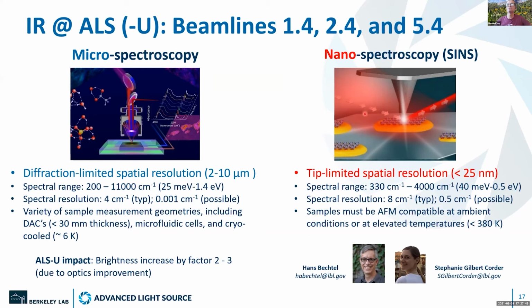This is a very ingenious trick to bypass the diffraction limit, in that the infrared beam is interfaced with an AFM tip. The scattering of the infrared beam off the AFM tip creates a feedback with the sample, and it's this scattered infrared beam that is analyzed with an FTIR spectrometer. With this, the spatial resolution gets limited to the size of the tip, to below 25 nanometers. Obviously, this technique is not so convenient to be interfaced with non-ambient condition samples, but it can still well be used for retrieved or quenched samples.